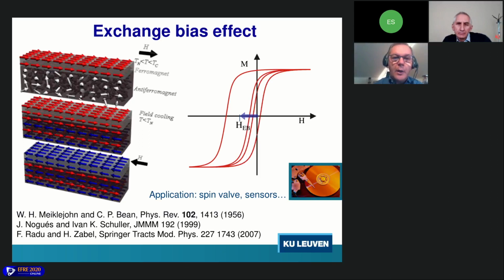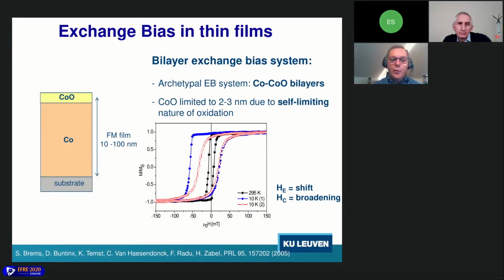Okay, so up to a couple of years ago, the simplest way of making such an exchange bias system is by simply making a cobalt film, exposing it to air, and then you get a very thin layer of cobalt oxide at the top. This is typically 2 to 3 nanometers thick, and it doesn't grow any thicker because of the self-limiting nature of oxidation.